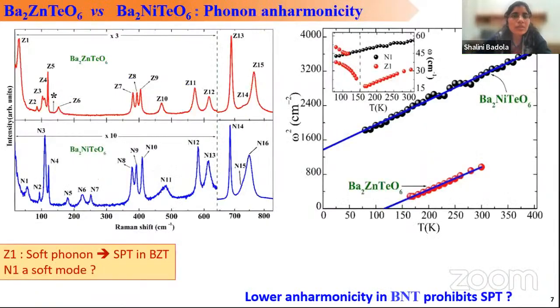And therefore, we also carried out temperature dependent Raman measurements on BNT, that is Ba2NiTeO6, where we found that the lowest frequency phonon mode, that is N1. From this figure we can see the room temperature Raman spectra of these two systems, where the phonon modes mostly match at room temperature. So we will now focus on the lowest frequency phonon mode because that is what is driving the phase transition in BZT. The lowest frequency phonon mode splits in case of BZT, while it does not split in case of BNT down to 80 Kelvin.